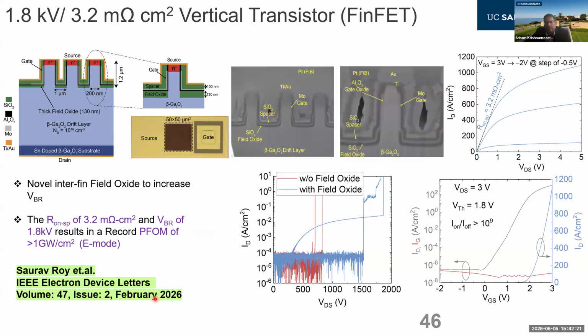And earlier this year, Roy in my group reported 1.8 kV transistors. So these are 1.8 kV transistors with 3.2 milliohm centimeter square on-resistance. And the novelty here is that we added a field oxide in the bottom of the trench. When you add a field oxide, this can result in enhanced breakdown voltage, as seen from this particular comparison. So without the field oxide, these devices broke down at 800 volts, but we were able to push it out to 1.8 kV by addition of the field oxide.